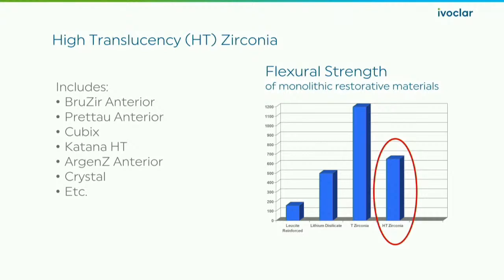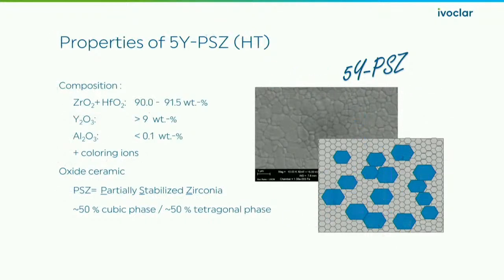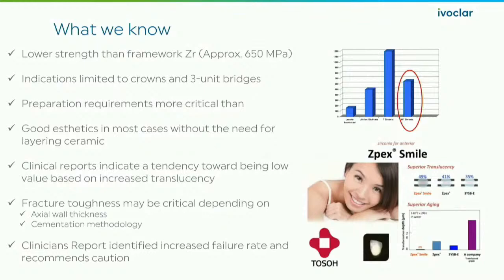So some of the HTs that are on the market, again, these are around the 650 megapascal flexural strength range. And again, about a 50-50 mix in the cubic phase. So where would we use them? Again, 3-unit bridges, similar indications as e.max, press or CAD. They've got good aesthetics. Don't need layering. You can layer them if you want. Micro layering, typically in the anterior; posteriors, you leave them monolithic, and you can do some nice staining and glazing and dial them in.